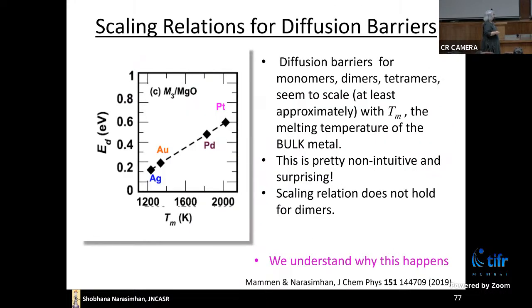And then we also found this strange relation, which is that the diffusion barriers for different metals scaled with the bulk melting temperature. Okay, except for dimers. So now I want to explain to you what a surprising result this is. You have one atom of a metal and it's going to move along a surface. But the energy it takes for that to happen is proportional to the temperature at which the bulk of that metal melts. And initially when we said this, the referees just howled in outrage and said it's impossible, this cannot be, this is an accident and all that. But we actually worked it all through step by step and showed where this relation arises from. And this gives you a very simple rule of thumb. If you do not want your nanoparticles to sinter, use a metal which has a high melting temperature.